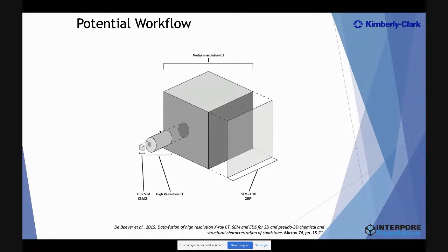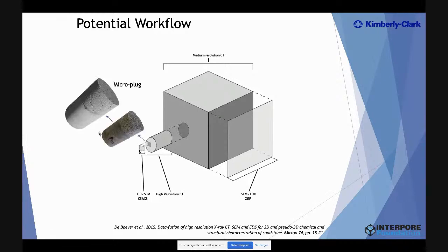And so what we typically do is we first scan a sample at a lower resolution to have an overview of our sample, and then depending on if we have interesting zones, we take subsamples and then we go for higher resolutions, and we combine this with other 3D imaging techniques. Like, for instance, if you have a microplug, in this case, that you scan at the highest resolution with your CT system, sometimes this is not enough and you need to go for higher resolution. Then we combine this with other techniques.